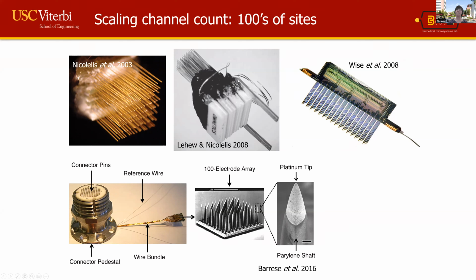And so, the scaling related to packaging becomes a bigger issue as you go to higher and higher channel count. This is also true of this Utah electrode approach, where you can kind of see a very thick, rigid wire bundle coming out of the back end and connecting to this very large connector. Both of these approaches on the left-hand side could take advantage of silicon microelectronics to be able to reduce the number of wires coming out. And this is by using just simple multiplexing. So sharing some lines and then just reducing the number of wires that come out.